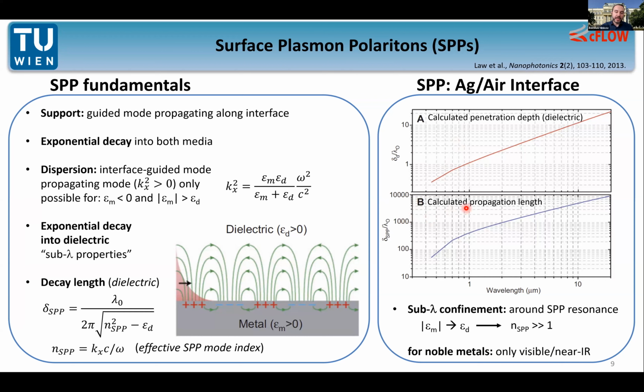We go directly into the calculated values of this propagation length. It's this lower plot here, and you see this is the propagation length as a function of the wavelength. So we see how many multiples of the actual wavelength at which we're looking, on the x-axis, the mode can propagate. And you see this increases significantly. Again, this is log scale, so be aware of that. It increases significantly, meaning that at a certain point in the mid-infrared, we can surpass thousands of wavelengths in this material.